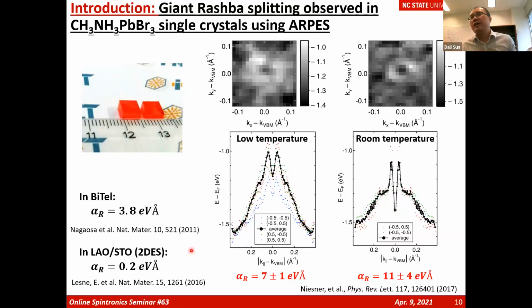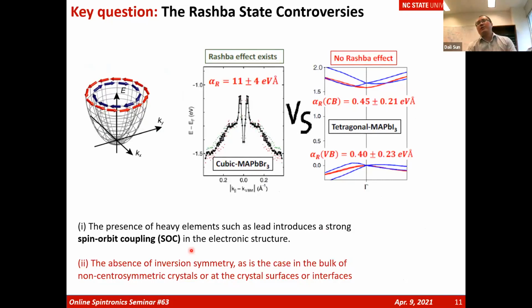As this report received lots of attention, experimentalists and DFT calculations further studied this structurally large Rashba effect in hybrid perovskite. Well, then the debate comes. Some research groups said, no, I'm even using the same ARPES, I'm not able to observe the splitting bands in the conduction and valence band. There's no Rashba effect. And for the DFT calculations, many research groups also repeated the calculation. They said, actually, maybe your Rashba state you calculate from DFT is due to error because your method is not correct. The Rashba state by their estimations is only like 0.4 plus or minus 0.2. Basically, it's negligible.